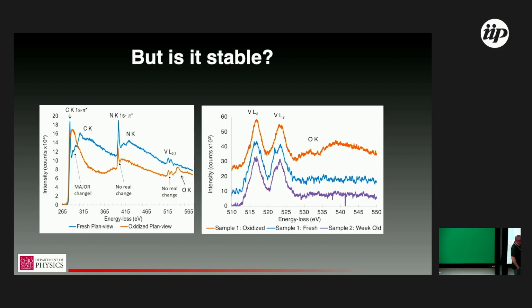That's bad. But even if you protect it from air, there's still some structural relaxation that takes place over longer periods. And so there's fun material synthesis things that I can dive into there, but I want to focus. That's not necessarily the focus of this tutorial, so I'll leave it at that. But the main message is that it does still age out if stored at room temperature on the time scale of about a month. And while that's not great in itself, it does point to interesting directions to improving the material, looking for other materials that don't have that effect. That being said, if you keep it cold and air-free, it's good for forever to first order.